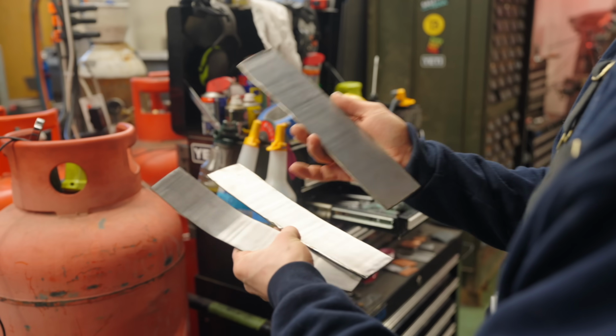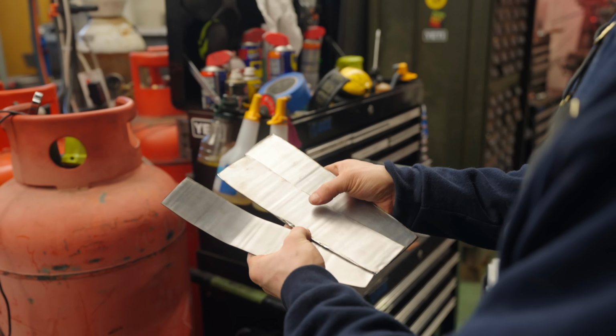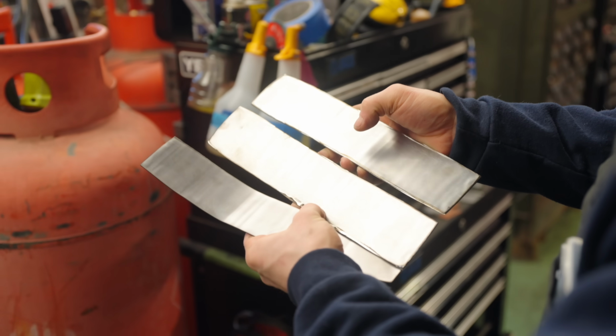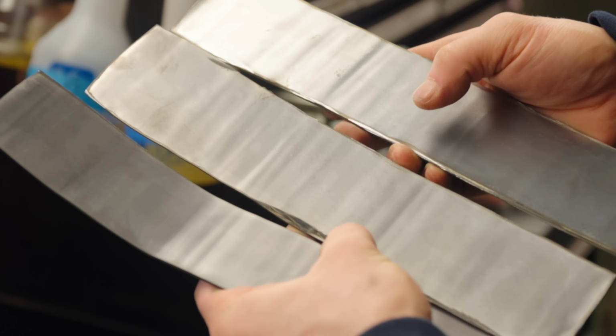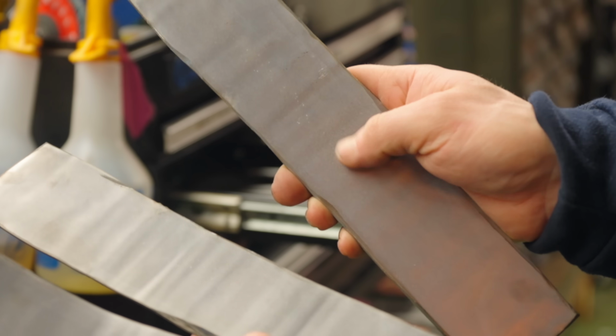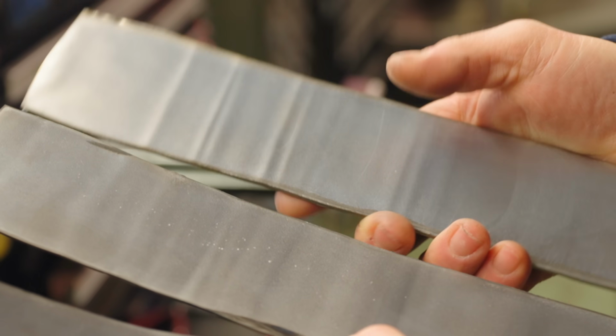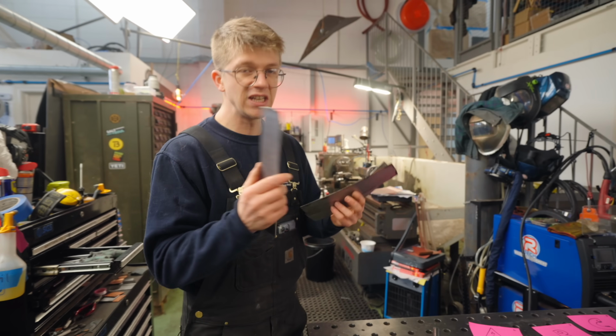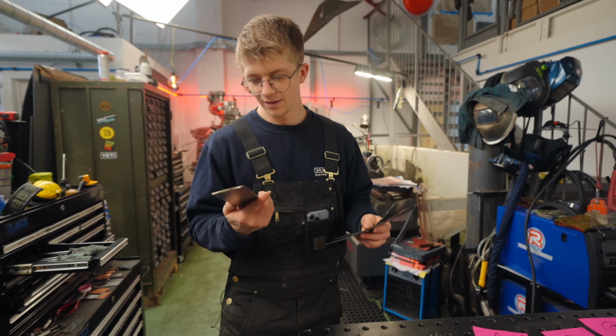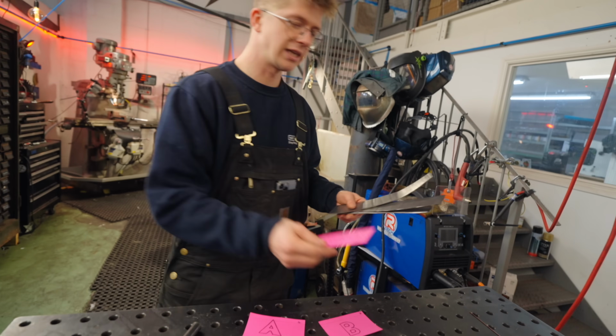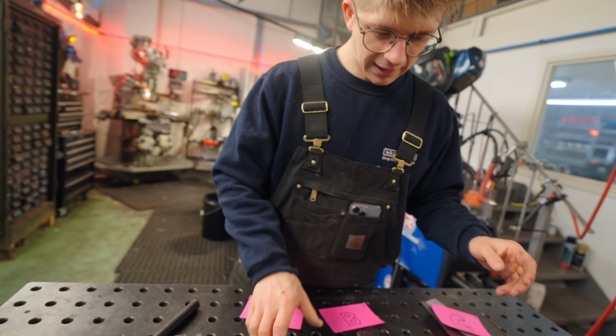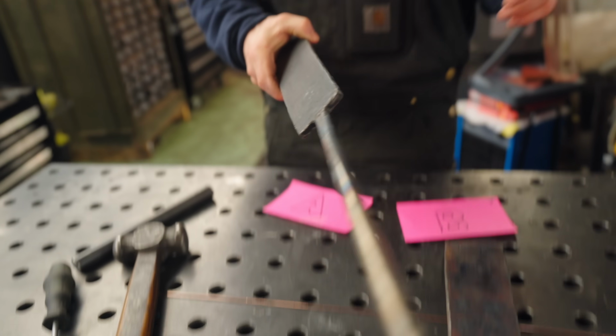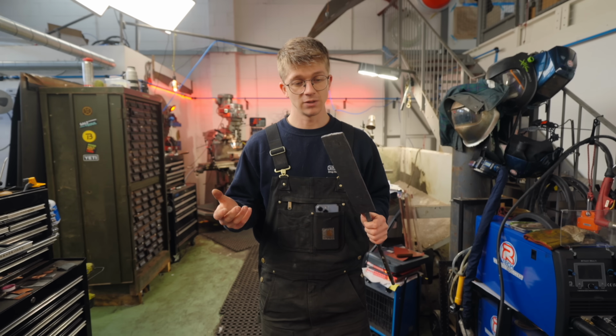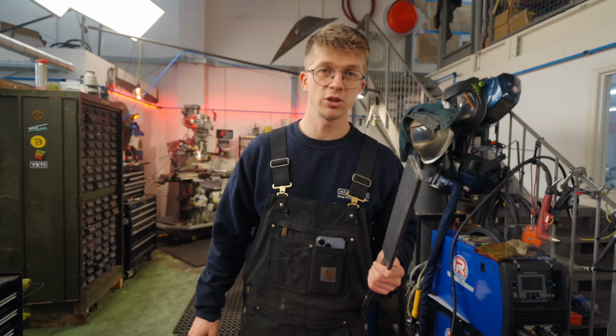Steel, titanium, titanium. Something definitely happened, because we do have this kind of telltale sign that the two did react together in some shape or form, because the steel has a coating stuck on it from the reaction with the titanium. Aside from that, there's nothing visually like, aha! There's your problem. So, unfortunately, experiment C, for no reason that's actually related to it being experiment C, is currently a bust. I say we crack into billet A and billet B. We see, do we have similar issues, or are they successful?